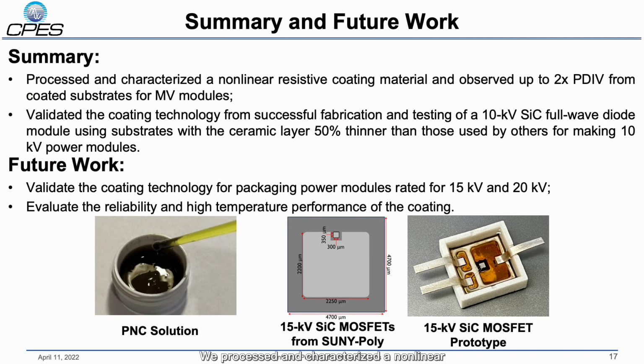So, summary and future work. In this work, we processed and characterized a nonlinear resistive coating material and observed up to 2 times PDIV from coated substrates for medium voltage modules. We also validated the coating technology in a 10 kV silicon carbide full-wave diode module using a substrate with a ceramic layer at least 50% thinner than those used by others for making 10 kV power modules.